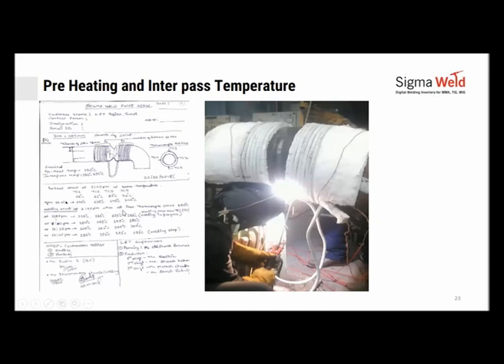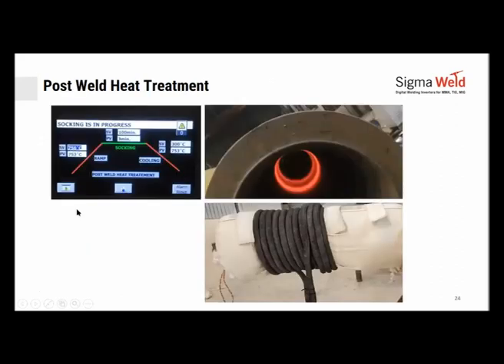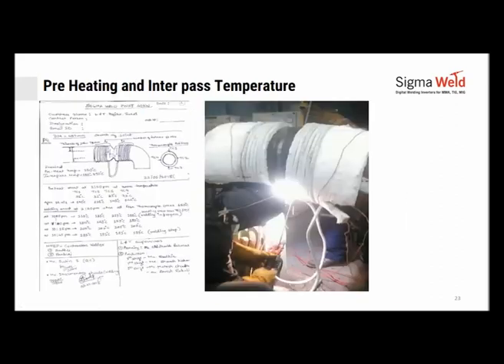They could start welding. All thermocouples all around, across the 12 o'clock, 3 o'clock, 6 o'clock, 9 o'clock positions, gave more or less consistent readings within 1 to 2 degrees. They started the welding. And during welding, as the temperature rises, they stopped the heating when they could. The time required to preheat was very less, as you can see, hardly 15 minutes. Setup time on something like this, again, would be not more than 15 minutes.